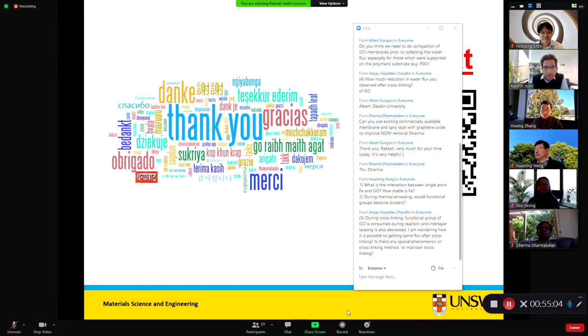What is the interaction between single atom Fe and GO? The Fe is very stable there, but we haven't used the Fe GO membranes for liquid separation yet. We used it for the electrocatalyst, before and after. Our characterization said it's stable, and they are just Fe, the atomic single atom there, in the atomic form. That's why it was a better catalyst.